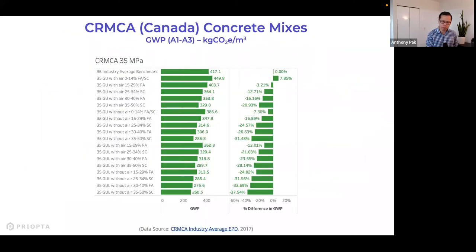their mixes. So just to give you an example, this is from the industry average data from the Canadian Ready Mix Concrete Association. If you compare against the benchmark, per meter cubed of concrete, if you use GUL, the Portland limestone cement, and you increase the SCM content, you can get up to 40% reduction. And then some of the local ready mix producers that have started producing their own environmental product declarations are getting close to like 50% or even beyond 50% reductions on some of these mixes. So there's a lot that you can do with concrete. It's not that all concrete is bad, but there's a lot of room to improve.